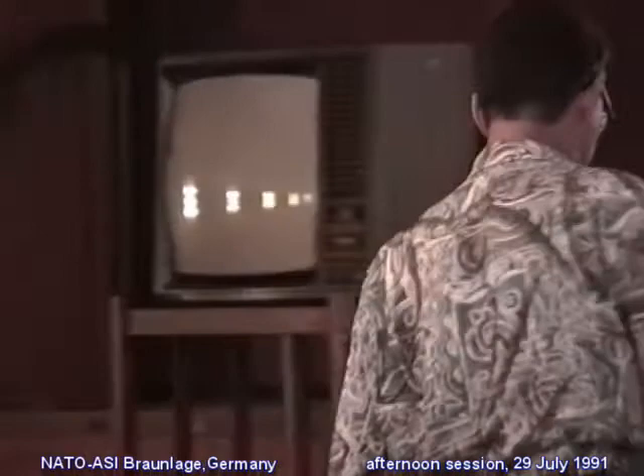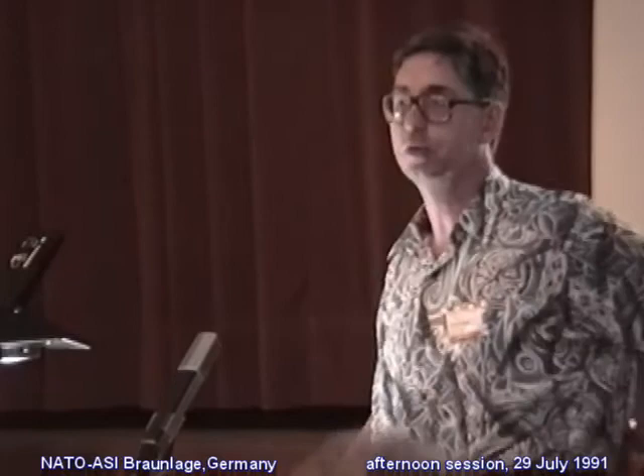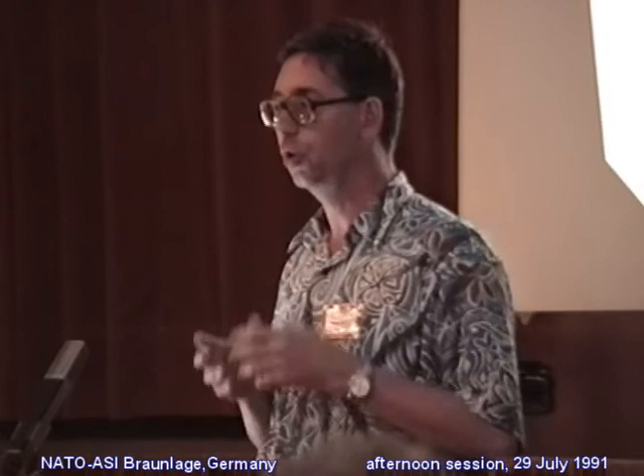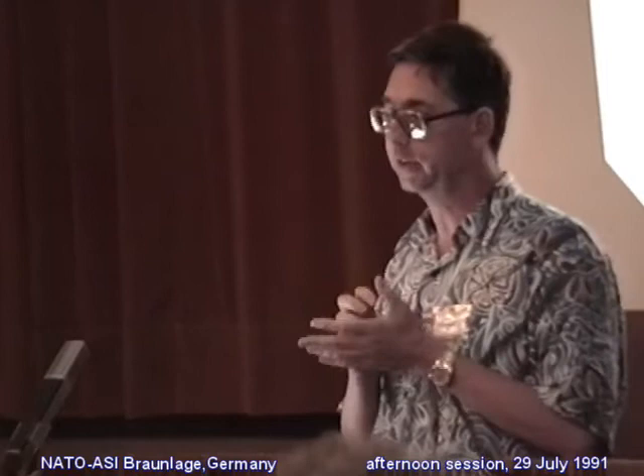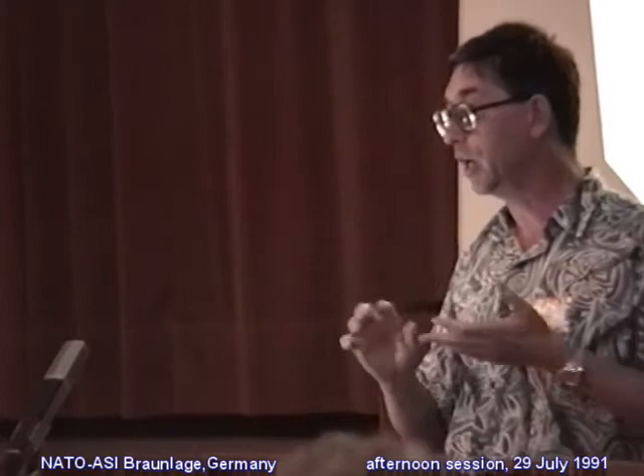Daniel Maugis from Paris. I would like to return to the definition of the coefficient of friction. It is usually defined as the ratio of the tangential force to the applied load, but it is the load applied by the experimenter. And it is not a good idea for a physicist, because in this definition we forget the load applied by the molecular forces. It is exactly as the friction of a magnet on steel. The friction coefficient may be very high, 100 or more. And you have the load applied by the experimenter plus the magnetic load. And it is the same thing with intermolecular forces. And the friction coefficient can vary with the load.